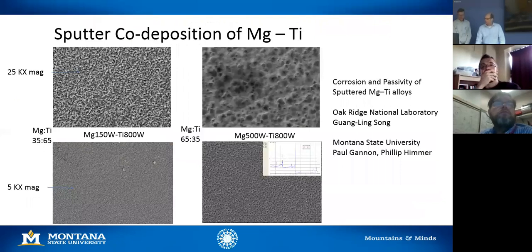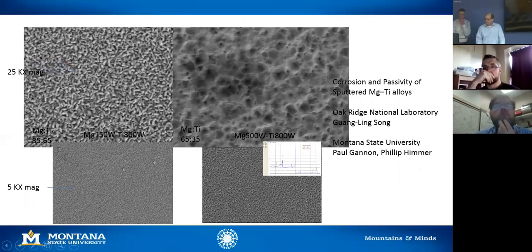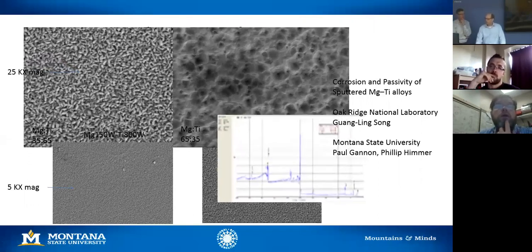Another project we did was with Oak Ridge National Labs, testing alloys, in this case for corrosion passivity of sputtered Mg-Ti alloys. We have a couple examples here of magnesium titanium with a stoichiometry of 35% magnesium, 65% titanium, and 65% magnesium, 35% titanium. Obviously a much different film as it's grown. And as you can see in a bigger picture, again, as this film grows through the alloying nature, the stoichiometry is much different. The way we're able to know what the stoichiometry is, is with the XPS.